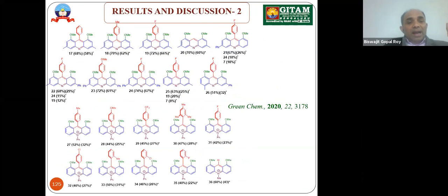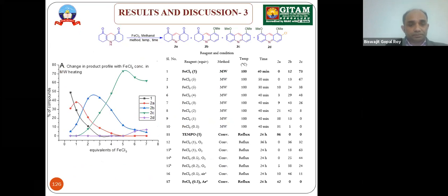So after the aldehydes, then we changed the diketones. We have taken several substituted diketones, and we found an increase in the yield. And after all these diketones, one more thing left is amine, change of amine. We have tried to change the amine also, and when we change the amine, the acridinium ions also form. So far there was not a single method which could make acridines and acridinium ions, but this method can make it. Okay, next slide, please.